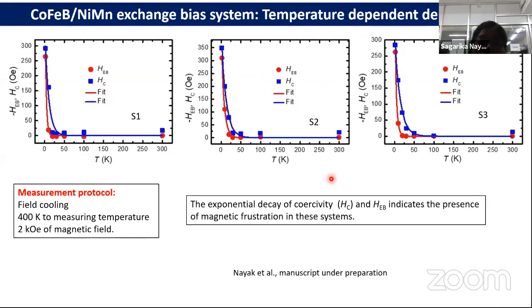Also, we performed a temperature dependent study, and we found a simultaneous exponential decay of exchange bias and coercive field with temperature, indicating that the interface contains both rotatable spins and frozen spins, which contribute to the maximum value of coercive field and exchange bias field simultaneously, indicating that the interface is frustrated.